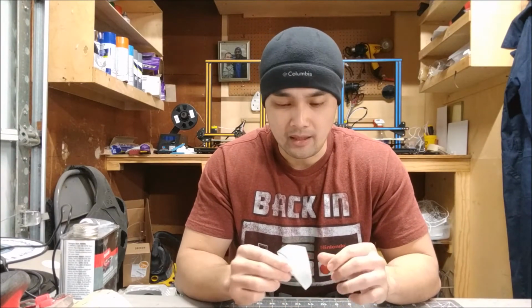Okay. So I had to raise my nozzle to 230 degrees. Again, this is for a 0.6 millimeter nozzle. I did not have a heated bed. I just put it on the tape. If you guys saw in the last video, it was all mangled.